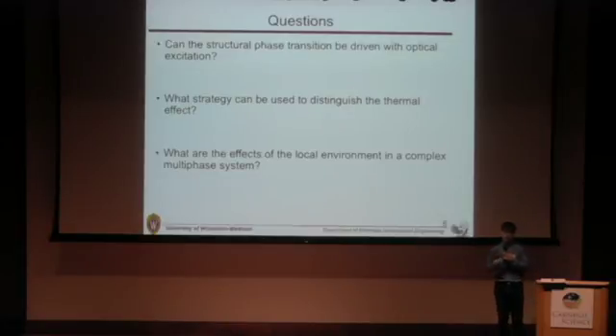Since we usually use an above band gap energy light source to excite the charge carrier, there is always a thermalization process because of the excess energy of the excited charge carrier, leading to heating of the sample. And it's extremely hard to separate the thermal effect, because the thermal effect can lead to the lattice expansion, and also the optical effect can lead to the lattice expansion.